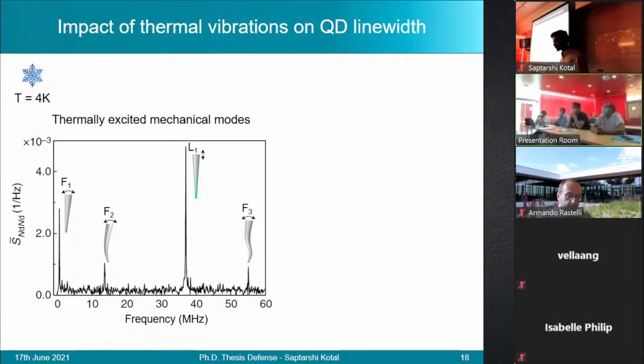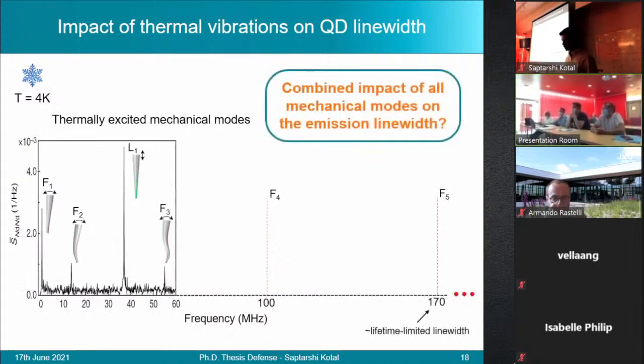So the experiment presented by Munch et al. allowed the identification of only the first few thermally excited vibration modes of the lowest frequency of the nanowire. But in reality, a much larger set of modes are responsible. The nanowire can support an infinity of modes. And so we set out to answer the question of to what extent the observed spectral broadening was due to only the vibration modes of a nanowire.